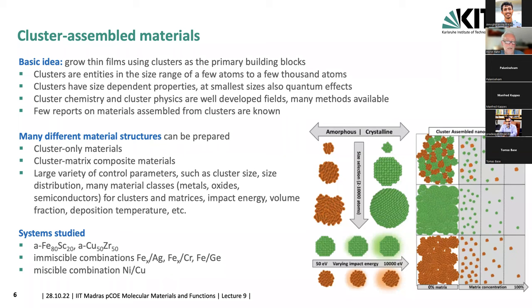This is less of a problem if we go to the second possibility, which is demonstrated over here, where we have the clusters embedded in a matrix. The matrix is not a cluster-based material, but it's, for example, a film which has been grown by atomic species, by just simple evaporation. But by co-depositing the clusters at the same time as the atoms of a different species arrive, we can embed the clusters into a growing film.